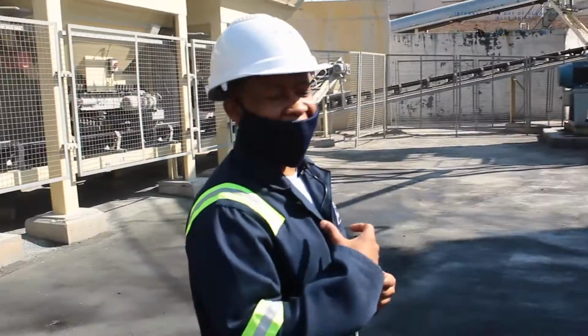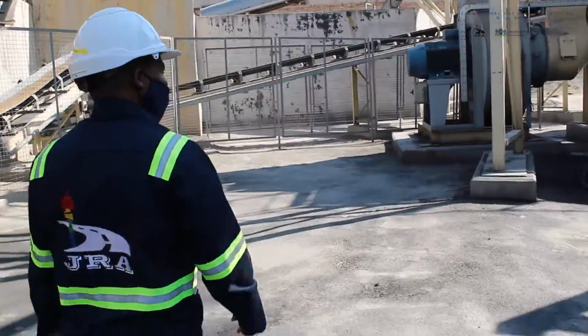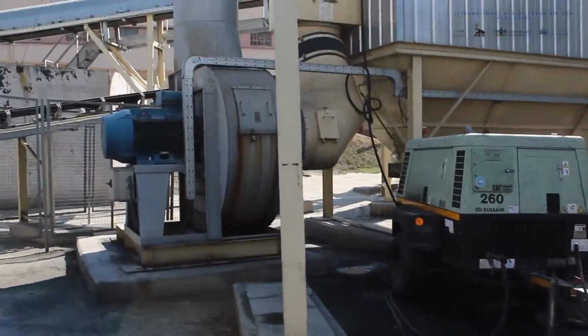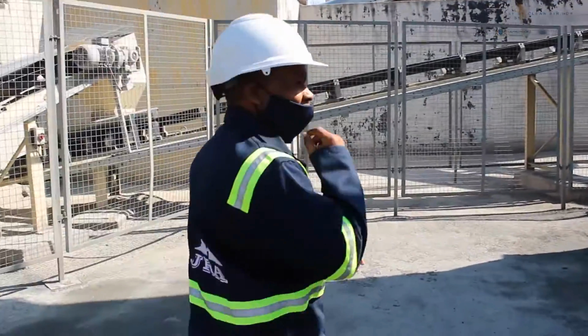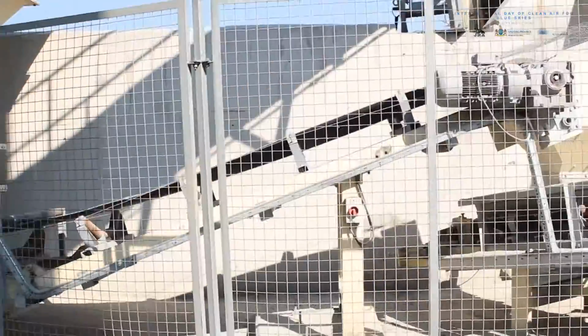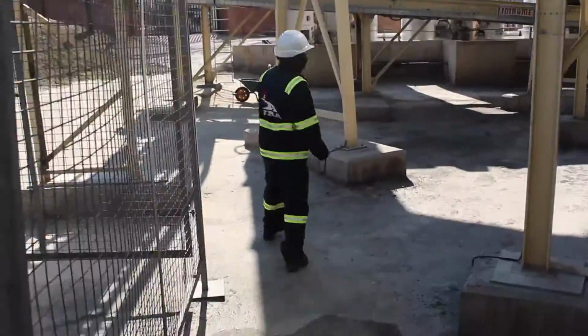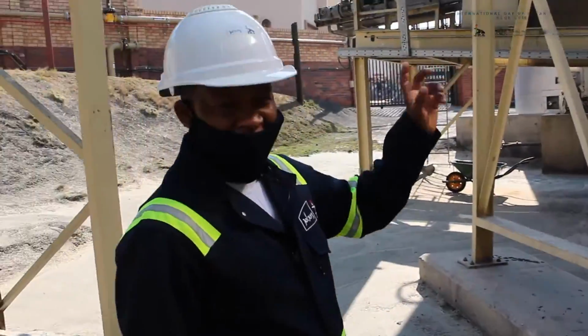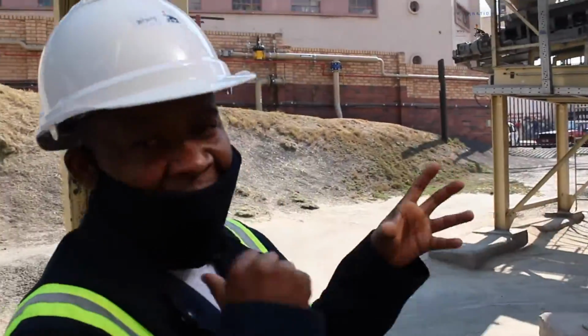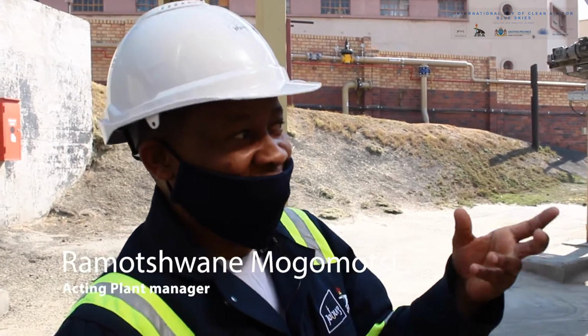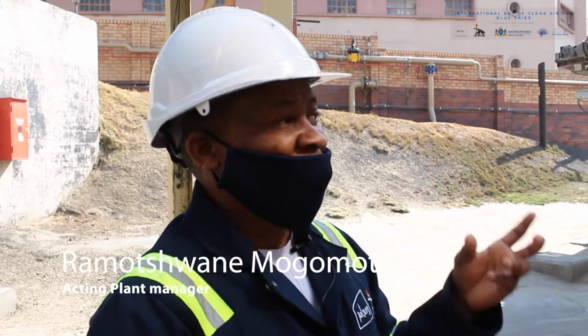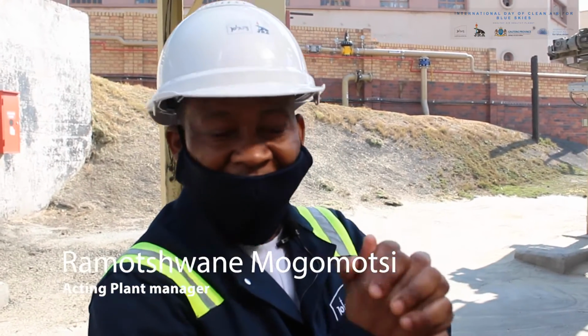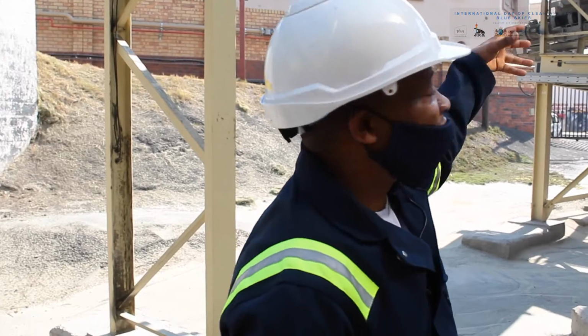Let me show you the mixing drum. That is a mixing drum, but we are going that side so that you can see it proper. This is a mixing drum. It's a drying drum. So that material that is coming in, we heat it up until a particular temperature, which is 160 degrees Celsius, so that it can be able to blend and bond with the bitumen. Now, this is where it comes in.